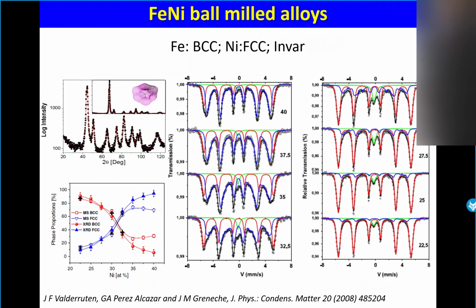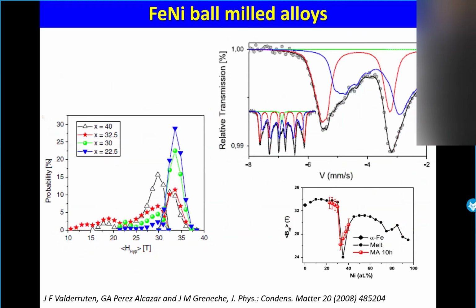Okay, we have also done iron nickel, to check what about the INVAR transition. And of course, with X-ray diffraction, we could distinguish BCC and FCC. In the case of Mössbauer, it was possible, but it was difficult to fit all spectra. We had to develop some model. And the model, as you can see, an extension is there. And you can see that we can observe again the INVAR transition in this system prepared by ball milling. What was very funny is that once I was in Tunisia, and someone was also working with iron nickel. I had obtained a few spectra, and I applied this model directly, and all spectra were fitted within 5 minutes, because the model had been prepared before for another situation.